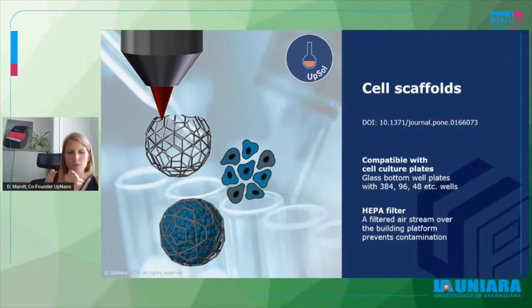So this is not a true bioprinting application, because you basically just produce the cages, and the cells are then combined in the second step together with these cages to end up with cell balls. These balls can again be fused, for example, to have a big agglomerate of cells and cell cages, which can be implemented, for example, in a defect area, to having the cell power and also then the support of the scaffold structure, so that they on the one hand side have a mechanical stabilization, and on the other side that they stay on the position they are intended to stay.